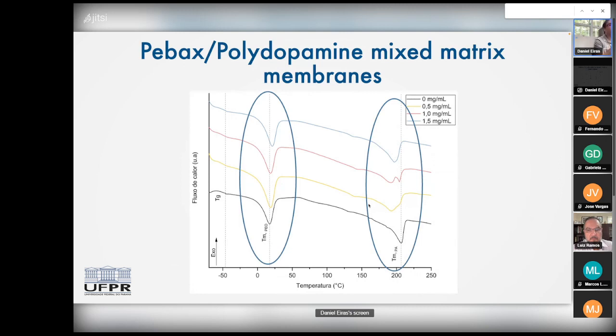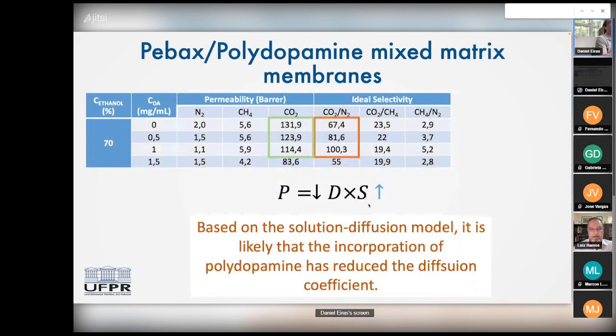So what we basically do in our group is to modify the material and try to understand what happens when you do that kind of modification. Usually, when you do composite materials, we end up with problems like that. The interaction of the different phases that form the material ends up influencing the properties of the membranes and giving us results that are different than expected. Again, we managed to increase the selectivity, but we did that by a decrease in permeability. So we did about half the work we wanted to do.